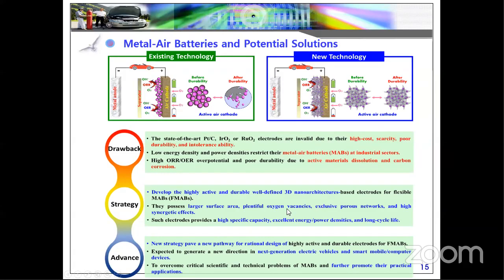and ORR properties. That catalyst should have high surface area and plentiful oxygen vacancies, because the oxygen vacancy is one of the challenging issues nowadays in the scientific society. Oxygen vacancy development is helpful to increase oxygen adsorption on the electrode surface. Then the porosity. The porosity is one of the challenges. This porosity is helpful to the electrolyte and electrode.